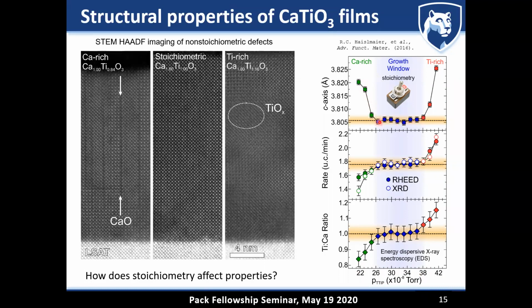You can see that despite the fact that we changed the fluxes, we did not change the out-of-plane lattice parameter. And then we confirmed this with energy dispersive X-ray spectroscopy, that really the titanium to calcium ratio did not change for films grown within this growth window. And this really shows that using this hybrid molecular beam epitaxy approach, we can go back to where molecular beam epitaxy works really, really well, which is accessing self-regulated growth windows.